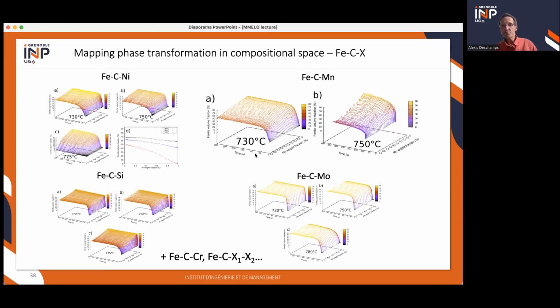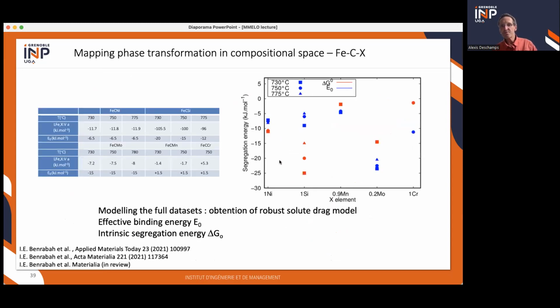And modeling the solute drag gives the possibility to access thermodynamic parameters, which were here, the effective binding energy between the different elements. So for the different elements, we're able to model the full composition gradients and different temperatures and see how much these effective binding energies depend on the temperature, for instance, and get also the intrinsic segregation energy, which does not depend on the presence of carbon.